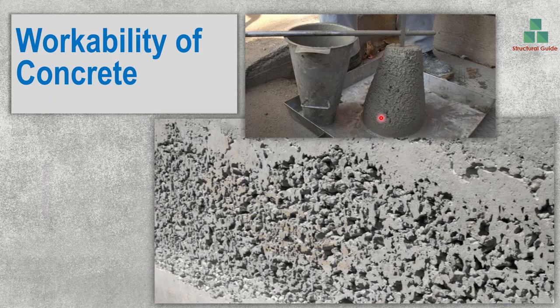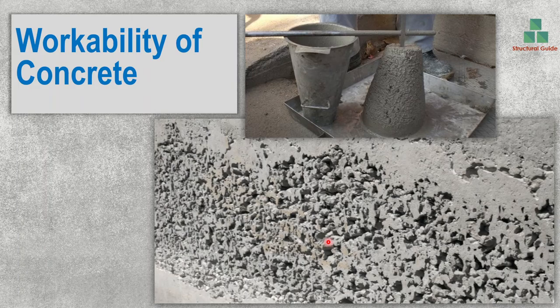With that, workability will be reduced. When concrete is less workable, even though you compact it adequately, the grout and the concrete aggregate mix won't blend properly. If the workability is less, the grout and the concrete mix could not achieve the required compaction. As you can see here, there are uncompacted areas. Even though you put the poker vibrator into the concrete, it could not compact properly due to the low workability.